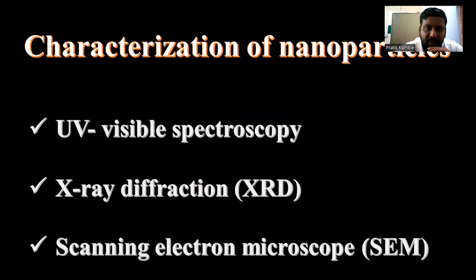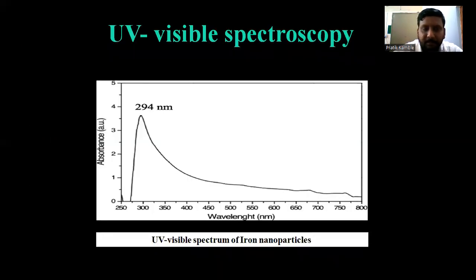Results and discussion. Characterization of nanoparticles. First of all, we have characterized the nanoparticles by UV visible spectroscopy, X-ray diffraction, which is XRD, and scanning electron microscope, which is SEM. UV visible spectroscopy: in this particular graph, we can see that there is a peak at 294 nanometers, which clearly indicates the formation of iron nanoparticles.